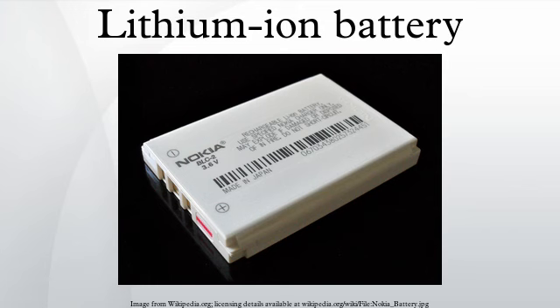In 1983, Michael M. Thackeray, Goodenough, and co-workers identified manganese spinel as a positive electrode material. Spinel showed great promise, given its low cost, good electronic and lithium-ion conductivity, and three-dimensional structure, which gives it good structural stability. Although pure manganese spinel fades with cycling, this can be overcome with chemical modification of the material. As of 2013, manganese spinel was used in commercial cells.